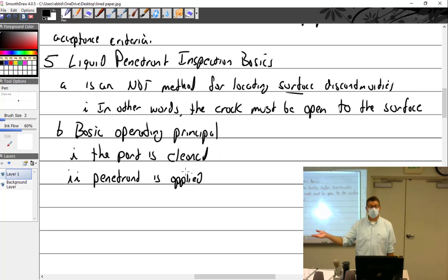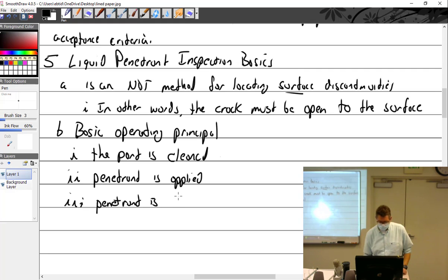Then you would spend a long time cleaning it with air nozzles and fresh water. For a crankcase, probably 15 to 20 minutes, just picking at it, getting all the bead out, making sure every passage is completely clear, with 100% no glass or plastic bead left. After that, it would go to the penetrant station. Once it's fully cleaned, penetrant is applied. Then penetrant is allowed to set, to sit on the part.